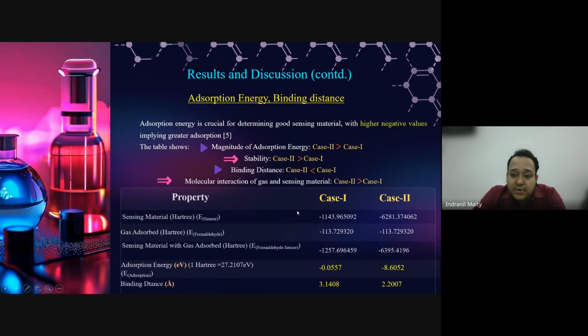In case 1, that is pristine graphene, and in case 2, that is silver doped graphene, the binding distance is reduced. In case 1, it is 3.14, but in case 2, it is 2.2. So the binding distance is getting smaller compared to the earlier case, which denotes a higher tendency to bind in the case of silver doped graphene. As a result, the adsorption probability is increased, so the energy is also significantly enhanced compared to case 1. So it denotes that the adsorption probability of formaldehyde on silver doped graphene is higher compared to the pristine counterpart.